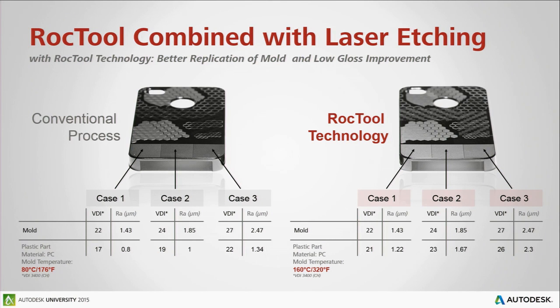And then this little square here is a 19 to 24, 22 to 27. From the same tool, and just turning the induction on right before injection for about 3 seconds, we ramp up to 320 F. That replication ramps up to 21, as you remember was 22. But look, as you go to finer textures, 23, 24, 26 to 27, it's almost 100% replication of your tool surface. What happens is then visually, the part stands out.